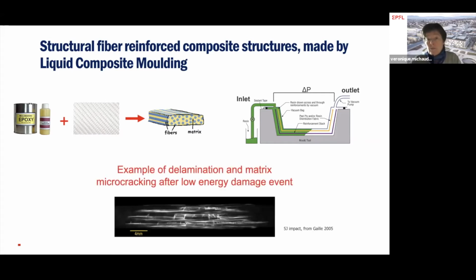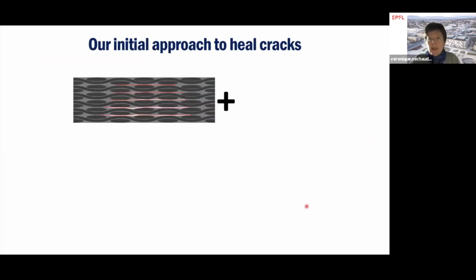And as an example of delamination or matrix microcracking after a low energy impact event, you see here in this figure, an X-ray picture after a 5 joule impact of a composite, that you have a lot of microcracks that are present inside the composite. They may not be so severe, but if you do not do anything about these, the integrity of the structure might be damaged.